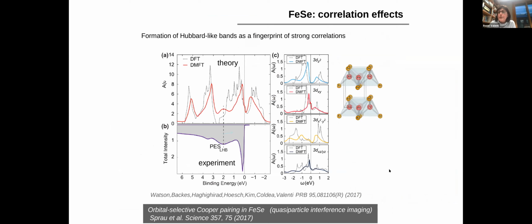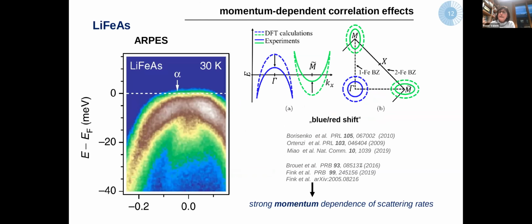And here I'm showing results for iron selenium, which is one of the materials thought to be most strongly correlated, where I'm showing the photoemission experiments from Amalia Coldea, Matt Watson and collaborators. And we did DMFT calculations here just to show that one can identify this transfer of spectral weight as a lower Hubbard band. And even more information can be obtained from these calculations by looking at the orbital selectivity, showing which orbital is most correlated and causing this effect of the lower Hubbard band.